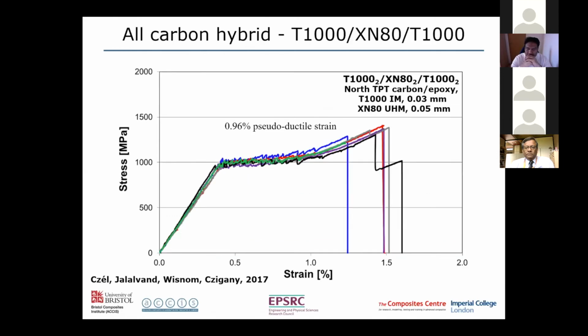We can also do the same thing with all carbon hybrids. Rather than using carbon and glass, in this case here we've used two different grades of carbon. We've used an XN80 high modulus carbon and a T1000 intermediate modulus, in both cases thin plies. And again, we see this pseudo-ductile response here with a plateau and about 1% of additional pseudo-ductile strain.